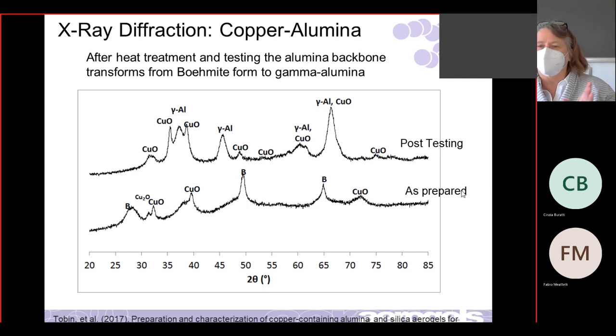So it allows you to identify that. And then we also saw copper oxide, CuO, and these peaks are related to copper oxide. So this bottom trace here is the as prepared sample. That's the one, that is this stuff. We hadn't done anything to it yet.